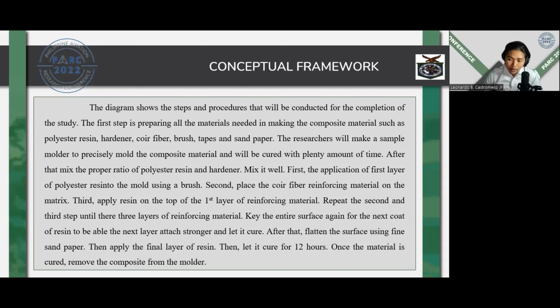Mix it well. Then first, apply the first layer of polyester resin to the mold using a brush. Second, place the coir fiber reinforcing material on the matrix. Third, apply resin on top of the first layer of reinforcing material. Repeat the second and third step until there are 3 layers of reinforcing material. Key the entire surface again for the next coat of resin so that the next layer can attach stronger, and let it cure.